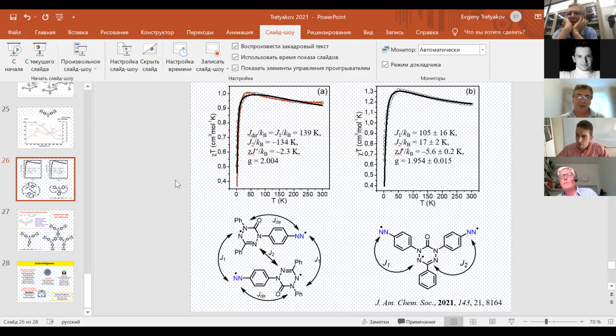In your analysis here, 1.954. It's very rare that these radicals show a G value below 2. Actually, it's related with, as I try to show you, maybe I missed this. Every time we obtain compounds with a solvent, with acetone molecules, and after on air, every time we have loss of these acetone molecules, and maybe this is a reason for some deviation from 2. So this is the ideal G value that we have to have. But